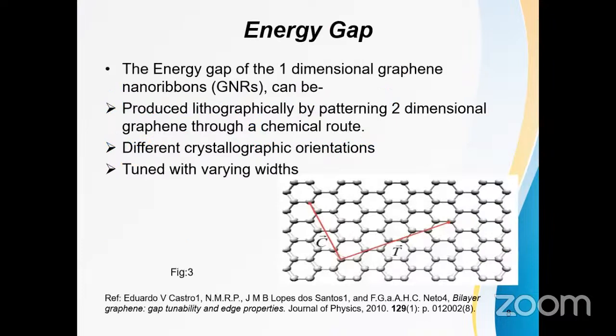We worked on the energy gap of the graphene nanoribbons, how the energy gap can be tuned. The energy gap of one-dimensional graphene nanoribbons can be produced lithographically by patterning two-dimensional graphene through a chemical route. When graphene is patterned into a nanoribbon and the carriers are confined to a quasi one-dimensional system, we expect the opening of an energy gap.